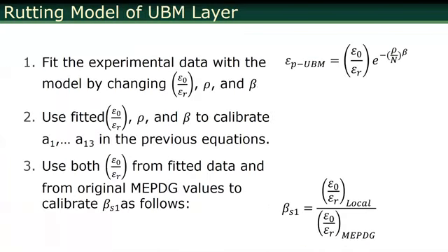So the way to calibrate is we fit the experimental data, which is like plastic strain versus cycles data, by using this equation, to come up with these values. These are like A, B, and C values, even though they look very complex with Greek letters and everything, this is like one constant, another constant, another constant.